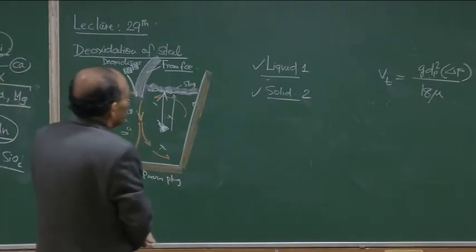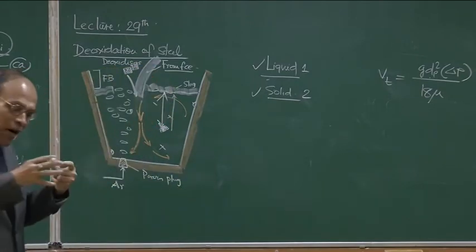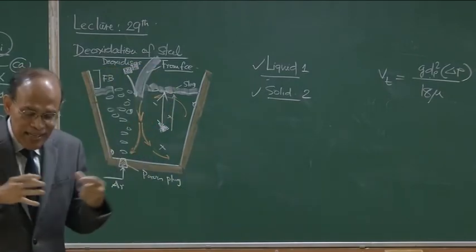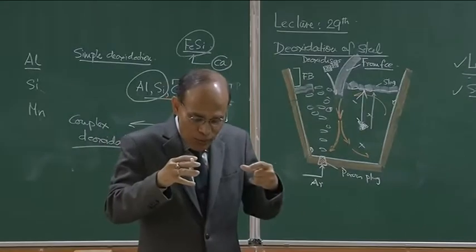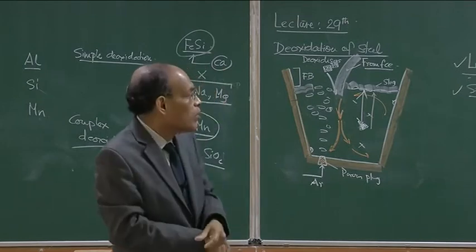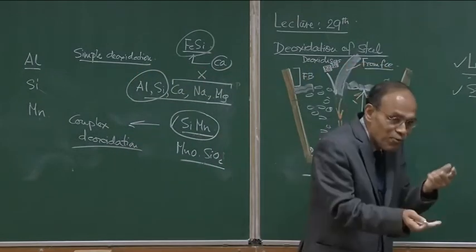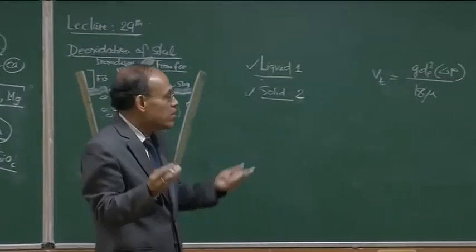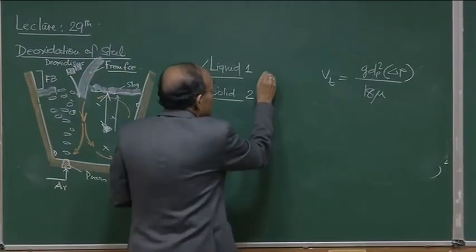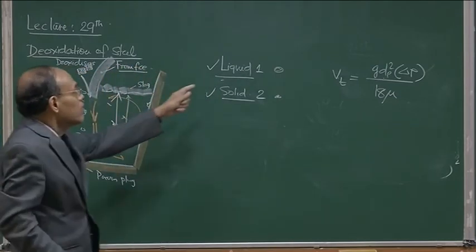On the other hand, the efficiency of coagulation or coalescence for solid particles is not so large, and as a result solid particles do not readily form bigger masses by coalescence, and they tend to float relatively slowly because of their diameters. These are smaller diameter particles, whereas liquid ones could be bigger diameter particles because of coalescence. So that is why they are desirable.